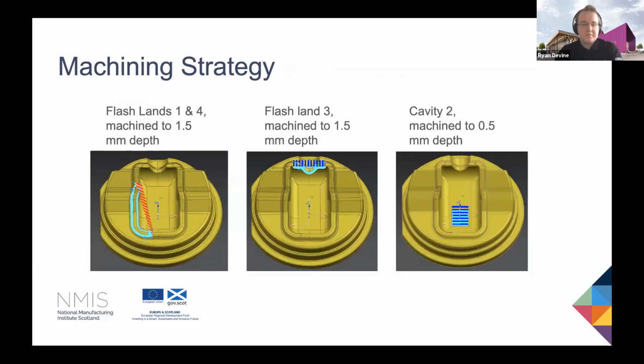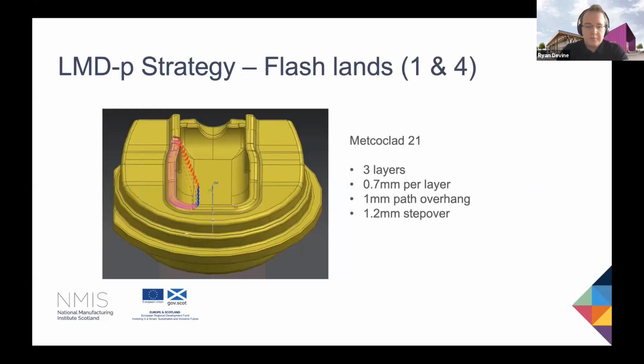areas. So from this, we identified that for flashlands 1 and 4, we had to machine to about 1.5 millimeters deep in order to remove any worn and damaged areas from the surface. Similarly at flashland 3, we also had to machine to about 1.5 millimeters deep. However, for the cavity in section 2, that only had to be machined to about 0.5 millimeters deep.